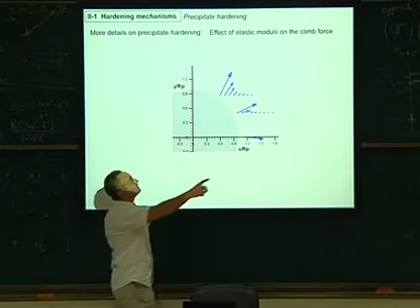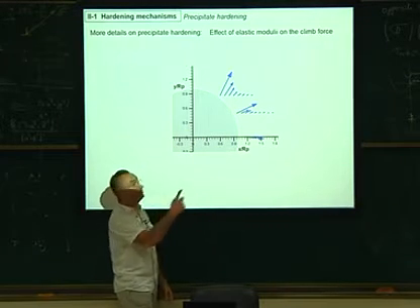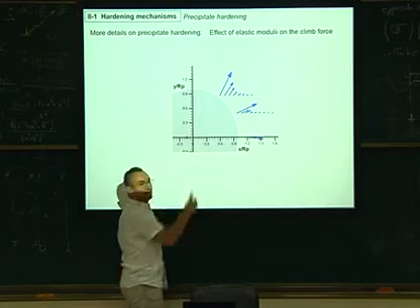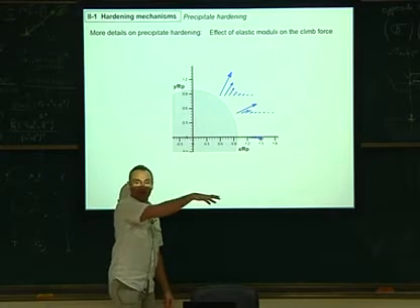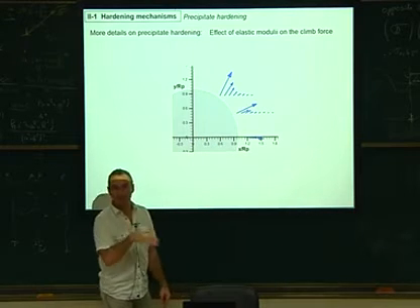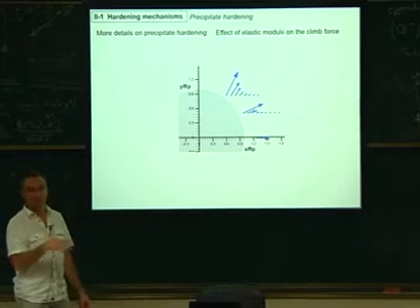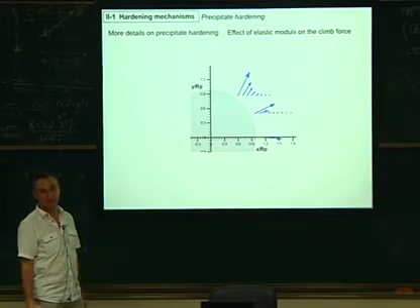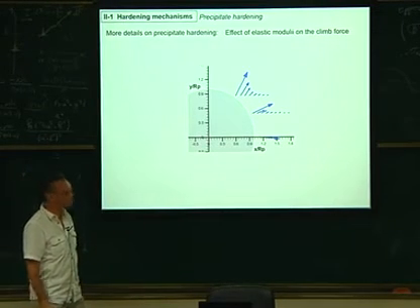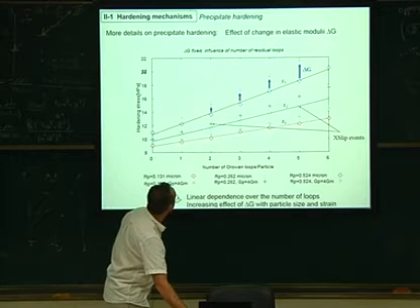So it means that when the dislocation comes, if the temperature is high enough, you will have some climb mechanism that will make your dislocation avoid the particles and make more plasticity. So this is a recovery mechanism for this particle hardening mechanism at high temperature. Okay? So out of that, we have the curves.